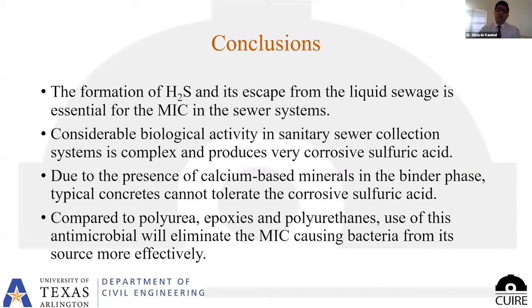So in the conclusions, I would like to say that the formation of hydrogen sulfide and its escape from the sanitary sewage environment is essential for MIC in these sewer structures or systems. Also, there is considerable biological activity in the sanitary sewer collection systems, which is a complex phenomenon and which produces sulfuric acid. And as we have seen in the previous slides, there is the presence of calcium-based minerals, which usually come from concrete as a binder phase, and it becomes hard to tolerate the corrosive sulfuric acid.